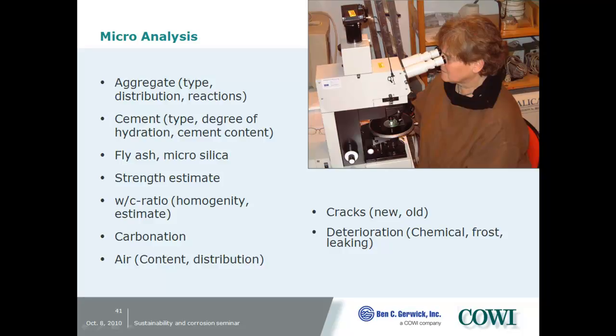Carbonation depth, air void content, distribution. Very, very useful. We can also evaluate whether cracks were formed in the young concrete or in the hardened concrete. That is a very strong tool when you want to evaluate what caused the crack. Is it a structural crack? Is it deterioration going on? Or is it a shrinkage crack, thermal crack from the early age?